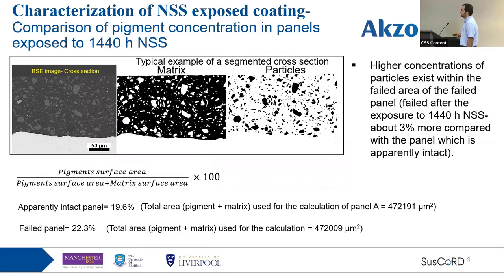I used ImageJ to segment the pigments of these coatings, and then I tried to calculate some estimations for the pigment volume concentration within these coatings. So the coating that showed failure appears to have higher concentrations of pigments within it, while the other panels showed lower concentrations of the pigment. And the difference is not significant, it's only 3%, but if you think that the percolation threshold for uniform spherical particles is around 16%, and since these particles are non-uniform with different size ranges, it may lead to a higher percolation threshold. So we may expect that the percolation threshold is within this range.